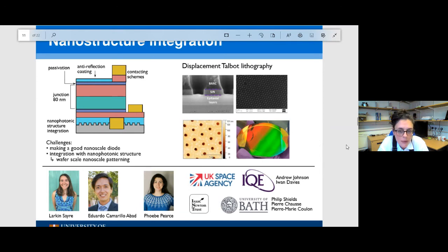One of our most promising techniques that we've been looking at so far is displacement Talbot lithography. So the main challenge is that we can't use conventional contact lithography methods for this kind of patterning. We need features that are on the 500 nanometer length scale, and you're simply diffraction limited in that regime. You can't image using contact methods.